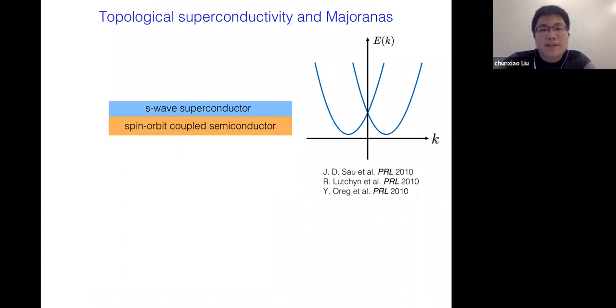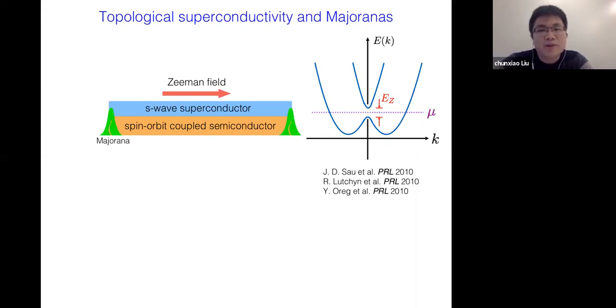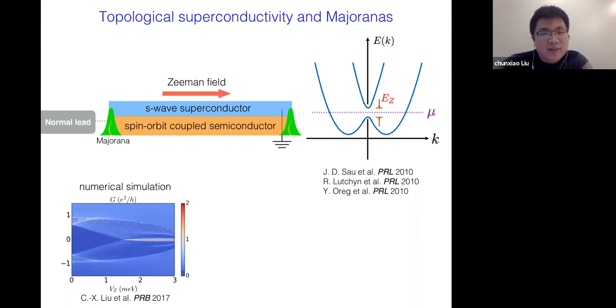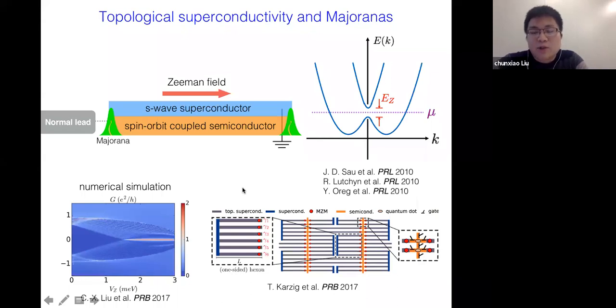Heterostructures between spin-orbit coupled semiconductors and s-wave superconductors are a candidate for realizing topological superconductivity. For a one-dimensional hybrid nanowire, when the Zeeman field parallel to the nanowire axis is strong enough, and the chemical potential of the nanowire is tuned appropriately, the hybrid system will become a 1D topological superconductor, hosting a pair of Majorana zero modes localized at its ends. One way to detect these Majoranas is to measure the tunnel conductance spectroscopy in a normal metal-superconductor junction. The Majoranas will manifest themselves as a quantized zero bias conductance peak in the conductance spectroscopy. And these Majoranas are non-abelian anyons, so they can be utilized for topological quantum computing.